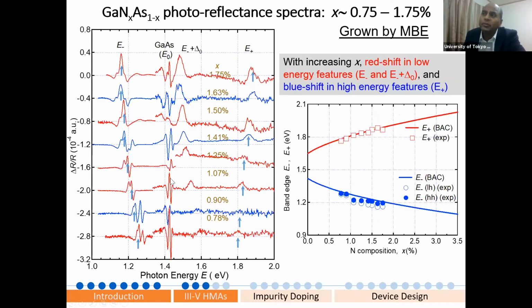And this is our experiment. These samples we have made by molecular beam epitaxy of dilute nitride, gallium nitride arsenide on gallium arsenide. And these signals are from our substrate, gallium arsenide. The horizontal axis is the photon energy, and the vertical axis is the photoreflectance signal. Here I want to show that this is the reference gallium arsenide signal. If you don't have any nitrogen, you get this kind of band gap. But if you have a little bit of nitrogen, and you increase it more and more, we have two bands.